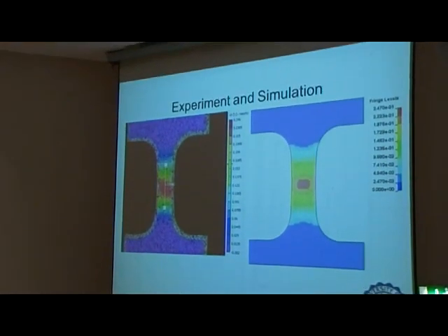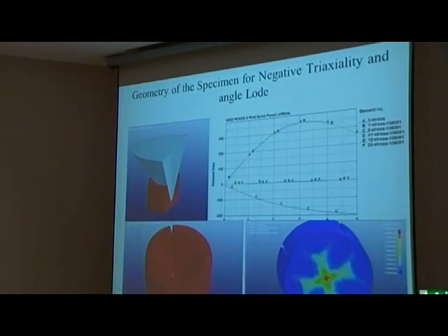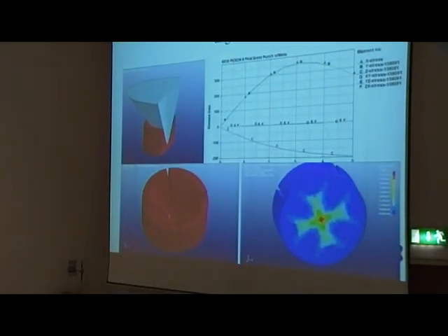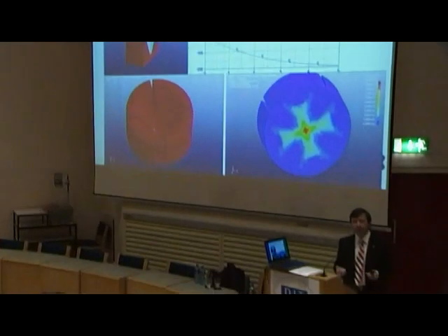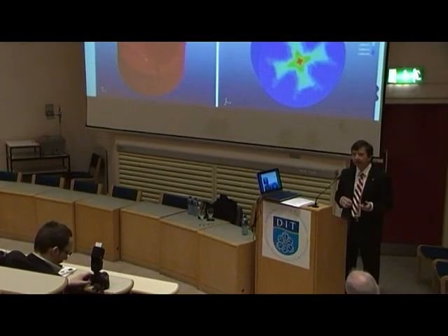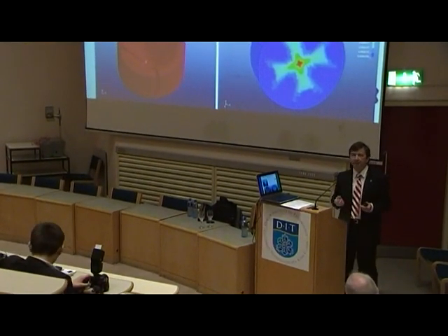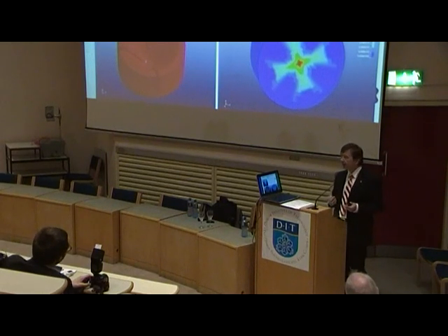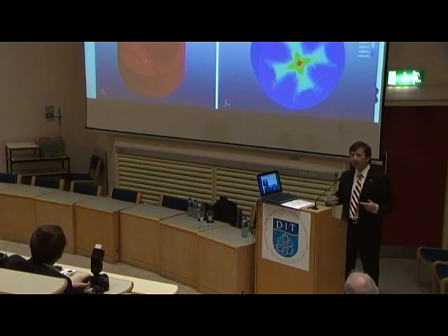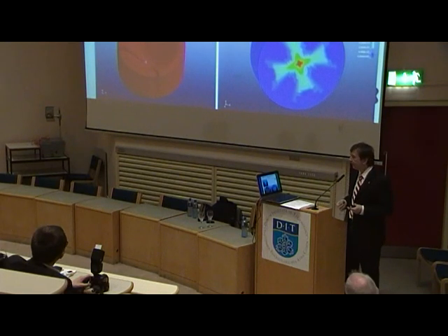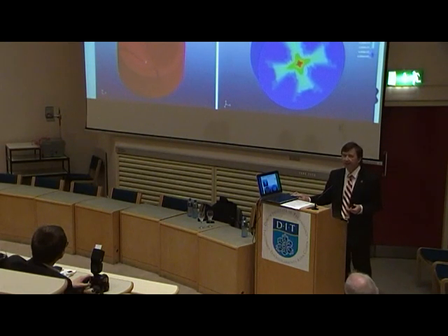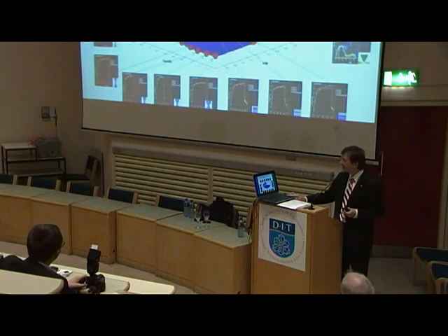And we can again observe this experimentally. And we developed a special specimen. This is a special specimen with a punch, and that punch expands the size of the specimen while at the same time pushing the bottom, and therefore producing the three-dimensional state of stress at the bottom, tension in X and Y, compression through the thickness. So this is the negative so-called Lode parameter or Lode angle and negative triaxiality.